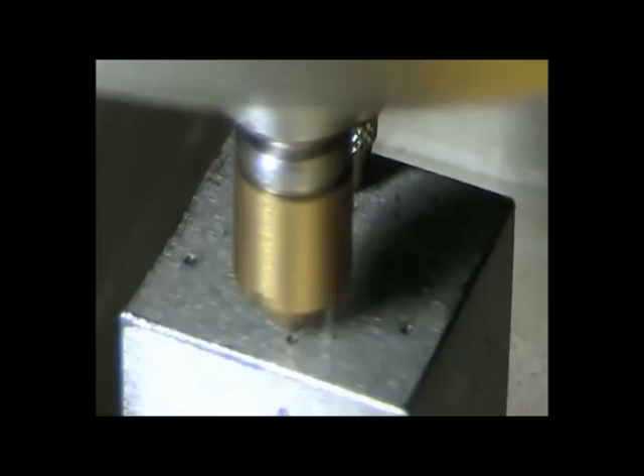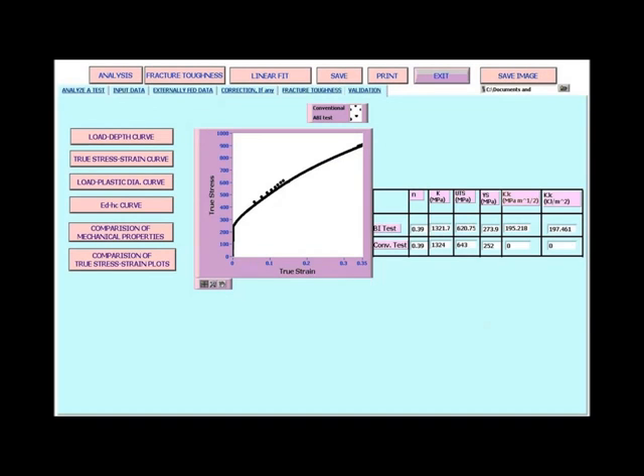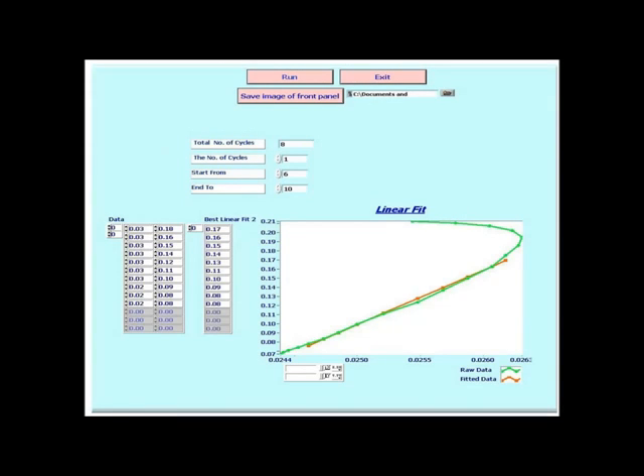Spherical balls of different diameters have been used to get multiple stress strain data points. For each loading cycle the total indentation depth is obtained corresponding to the maximum load and the plastic indentation depth is obtained after completing unloading.